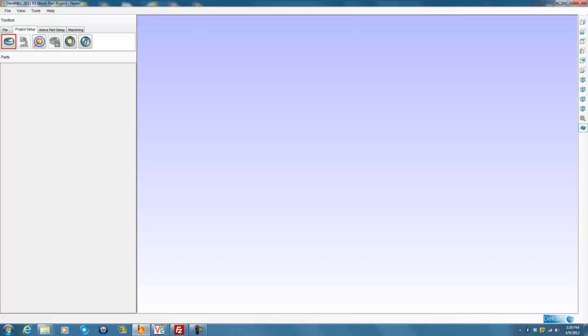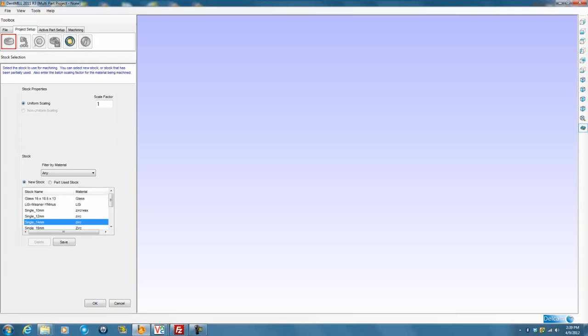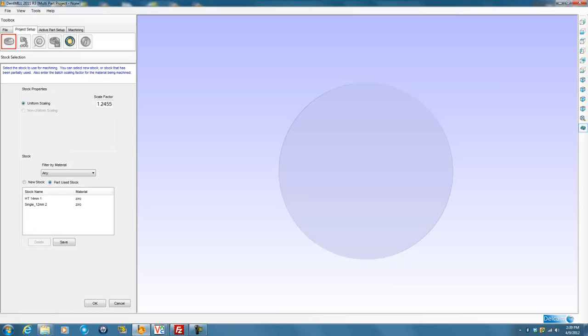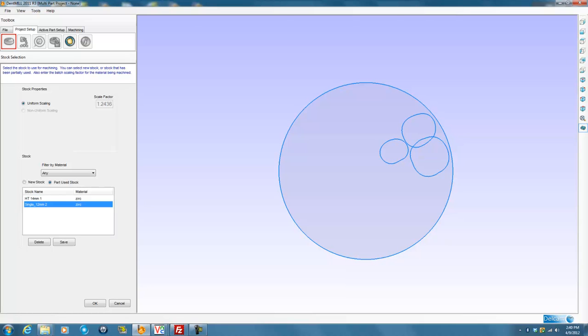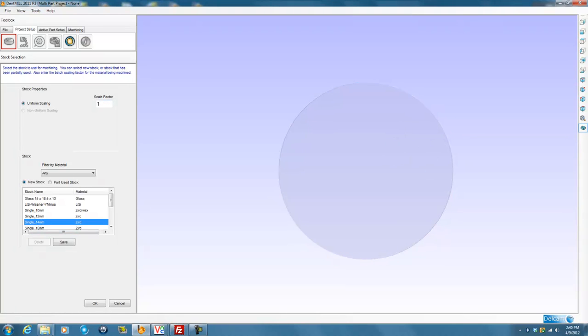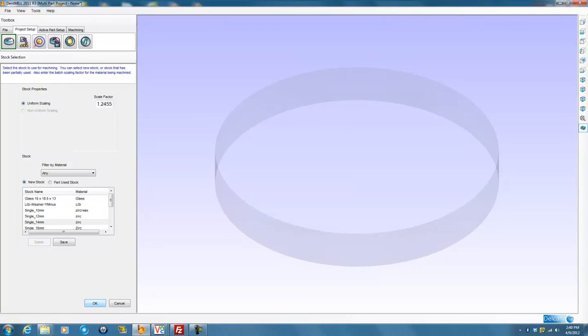The next part of the process is to select the size stock you need for these particular units. In this case, we'll select a 14mm with a shrink rate of 1.2455 zirconia. If I wanted to use a part-use piece of stock, I can get it from the list, and you can see it will include the holes made earlier. But I'm going to go back and select a new one at 1.2455 — this is the number that is on the zirconia disk. Then we hit OK. All of the units imported into the stock will be increased in size by that 1.2455 shrink rate.